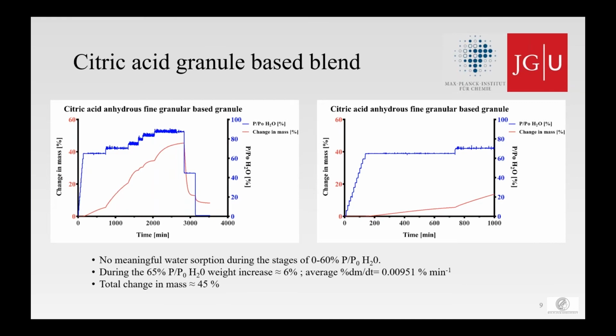So next would be the granule. Here you already observe a difference because there was no meaningful water sorption until the stage of 60%, in contrast to the powder, which already took up water at 60%. And then during the 65% stage, the granule also took up some water, but in contrast to the powder, it was only roughly 6%, so roughly half of the amount of weight gain. And also the mass gain per time, as you can see with the average DMDT, was slower. So the mass gain was slower and the total mass gain was less. The total mass gain after all stages was 45%, so there is no big difference there.